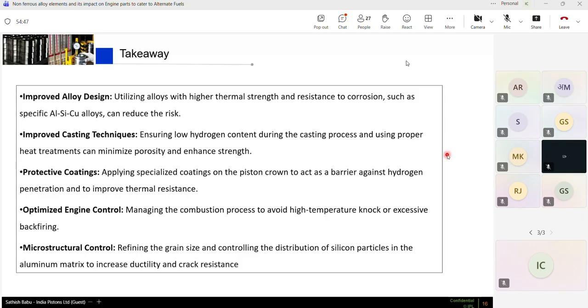Beyond that, as a supplier and as a manufacturer using aluminum alloys, we have a lot of challenges in refining the grain size and controlling the distribution of silicon particles, because a larger amount of silicon particles is also very dangerous in terms of durability of the parts and other things. So the matrix and grain fine structure and reduction of casting defects will definitely help to reduce the wear and other fatigue related issues in the parts.